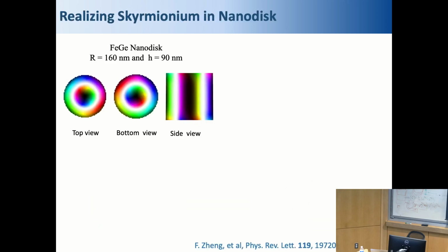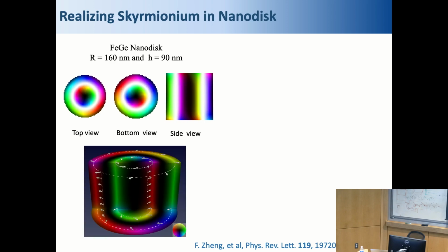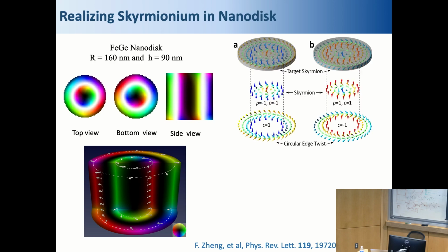This target skyrmion can be realized in a magnetic nanodisk, an iron germanium nanodisk. So we did some simulations, showing the top view, the bottom view, and the side view. So there's a skyrmionium that can be stabilized in an iron germanium nanodisk with a finite height. And this can be even stabilized in the absence of external magnetic field. Geometrical confinement is a good thing for the formation of this complicated structure.